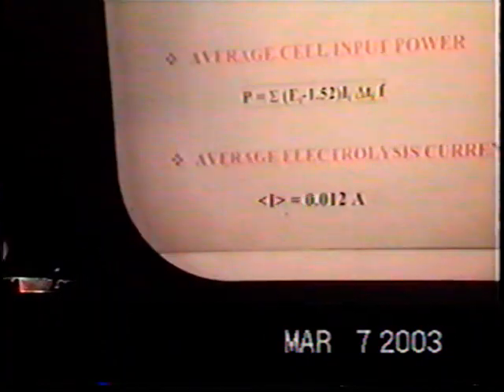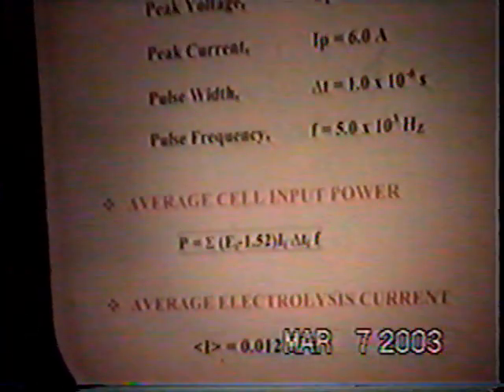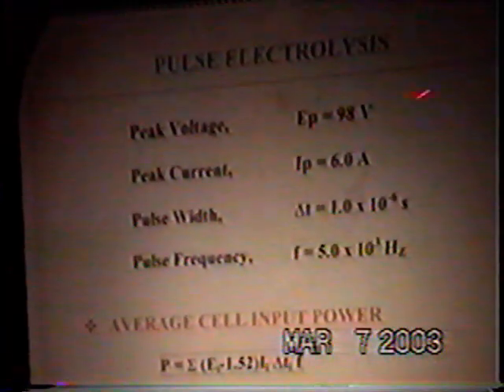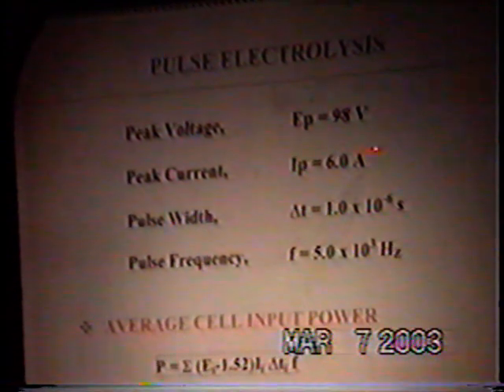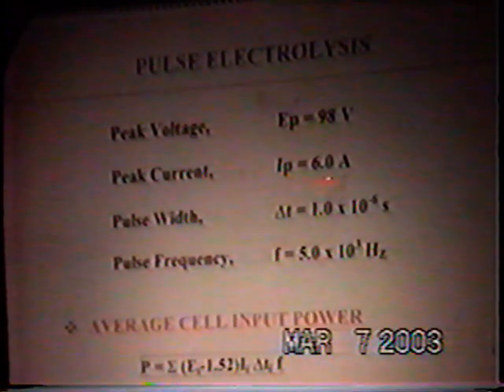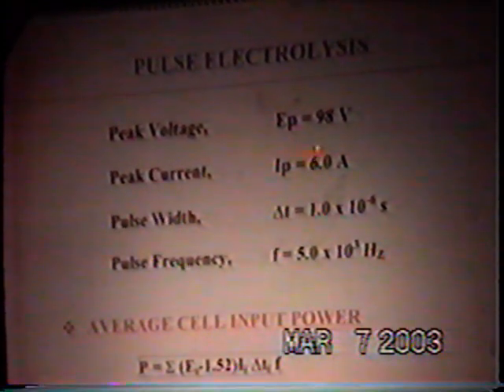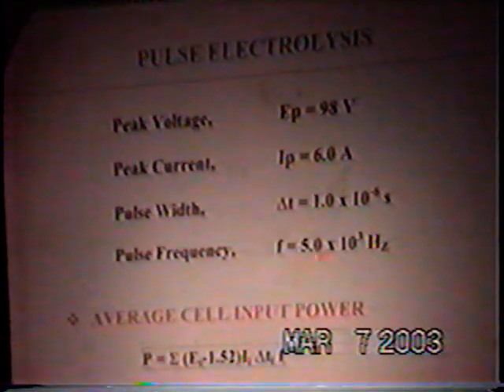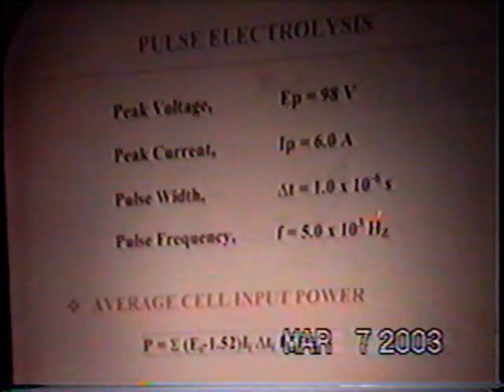This shows some of the conditions which I just mentioned. The peak voltage was 98 volts. The peak current, I guess that was 6. If you read off the scale, it was 6 amps. The pulse width was 1 microsecond. The frequency, in this particular case, was 5 times 10 to the 3rd hertz.